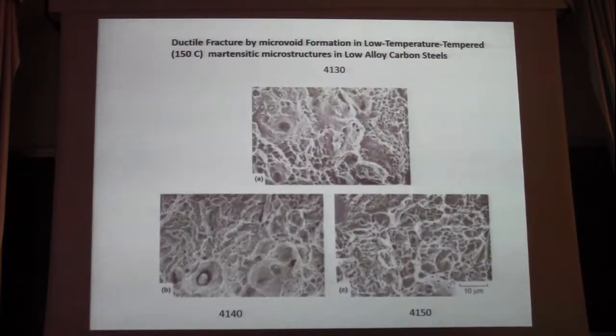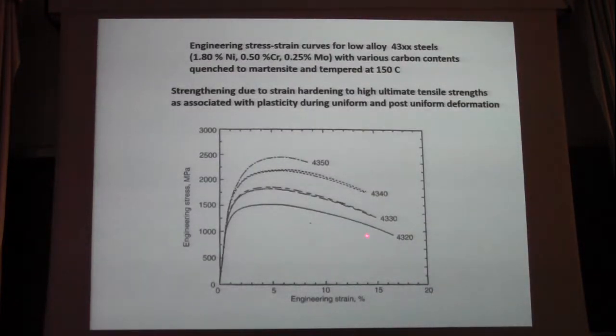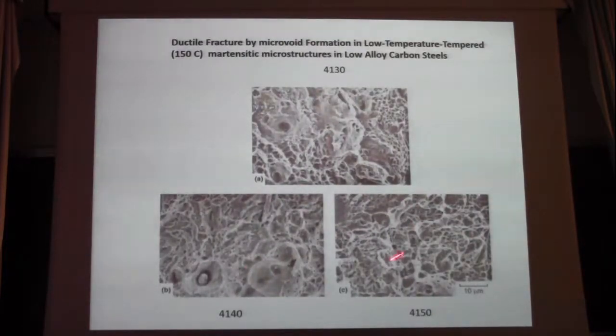And this is what ductile fracture is all about. Once you reach the instability point, in other words, where strain hardening can't keep up with the applied load, then you start to initiate voids. The dislocations pile up around hard particles, and microvoids are nucleated, they grow, and ultimately they grow together. And here's ductile fracture of those steels that are shown. Microvoids. This is the post-uniform fracture deformation.